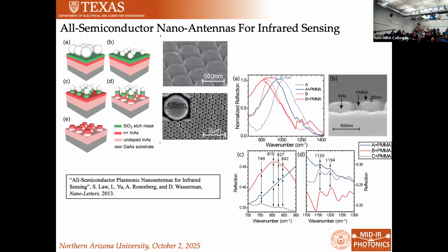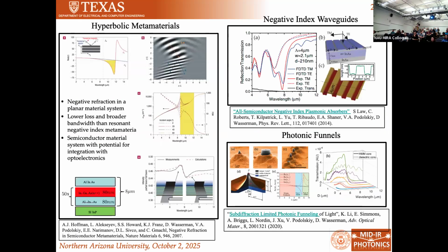We can even make little plasmonic nano antennas out of these, right? These are nano antennas that operate at 10, 11 micron wavelengths, but they're only a couple hundred nanometers in dimensions, right? So we can leverage all these different regimes of operation of our doped semiconductors. We can even stack our doped semiconductors with undoped semiconductors to make these hyperbolic metamaterial structures that bend light with a negative index of refraction. We can make negative index waveguides, and we can even take these metamaterials and fabricate them into funnels, and we can effectively funnel our 10 micron light down to nanoscale tips, through these metamaterial funnels into these structures.